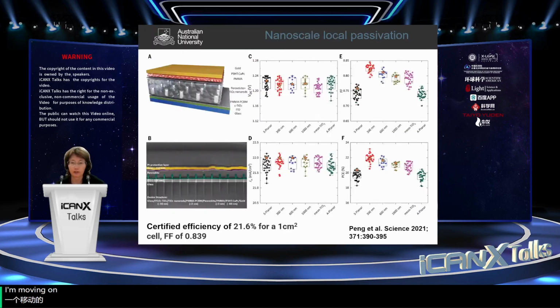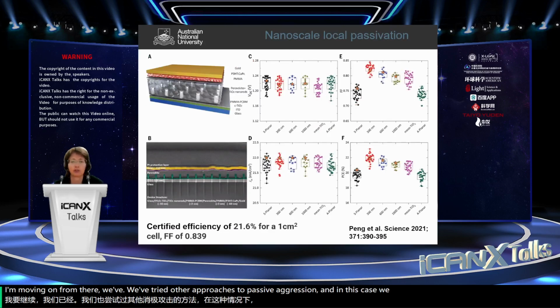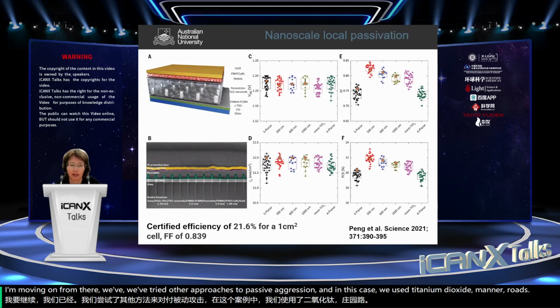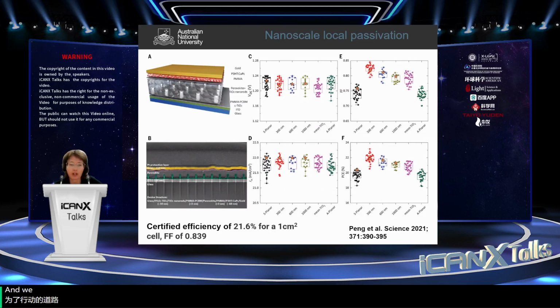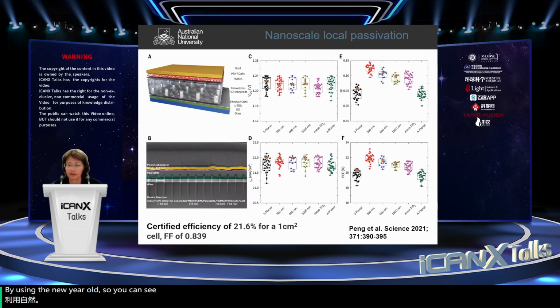Moving on from there, we've tried other approaches to passivation, and in this case, we used titanium dioxide nanorods for passivation. We coated the nanorods with the PMMA PCBM passivation layer. What we found there was that we were able to get a particularly high fill factor by using the nanorods. You can see, comparing the planar cases with the nanorods, you have a very much higher fill factor. At the time, that was the highest efficiency for a 1 square centimeter cell.